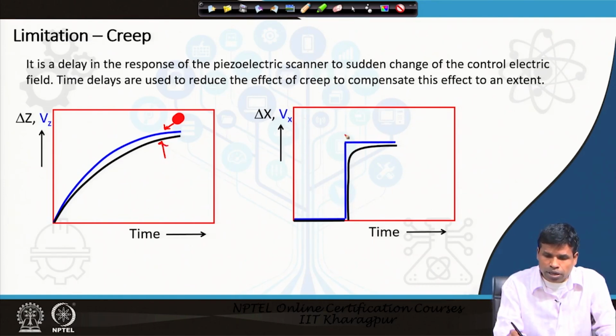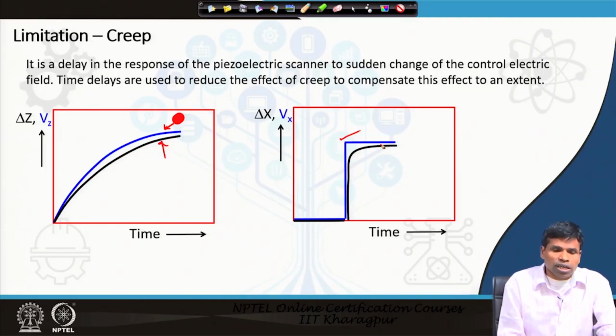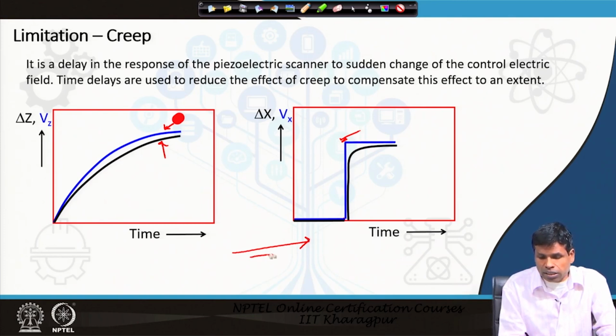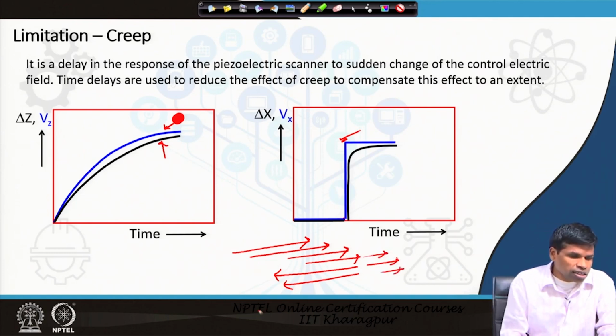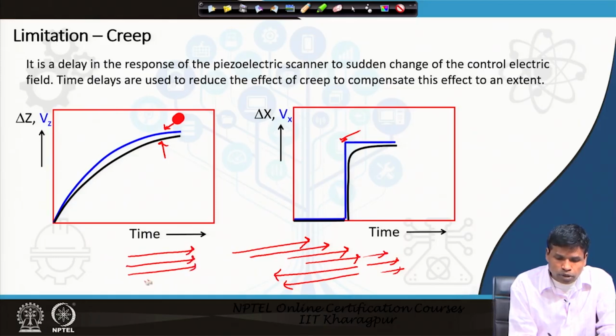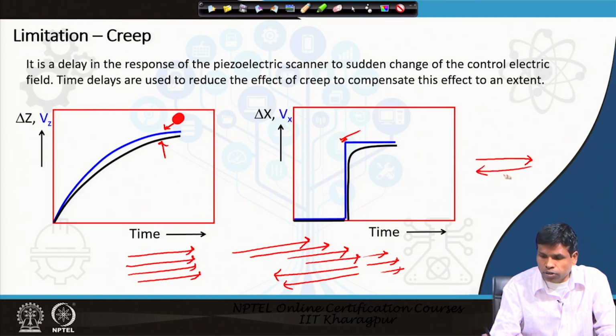Similarly, when we are increasing a voltage V here, you see how the displacement along the x direction, and this is also one of the limitations. In the absence of the creep, the displacement would go exactly to the same position. And this is another reason why, for example, if we want to move the piezoelectric scanner towards the x direction, we apply the positive potential, and the tip starts moving towards the positive direction, and when we again start bringing the piezoelectric scanner in the opposite direction in the negative scale, still our tip will be moving towards right. This happens, and that is one of the main reasons in the STM we scan from left to right like that, instead of going left to right, right to left like this.